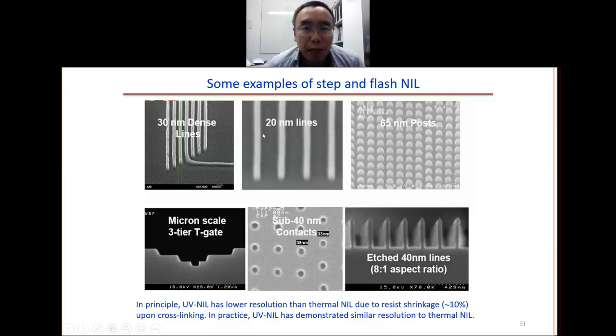Here 30 nanometer lines, 20 nanometer lines, 65 nanometer pillars, 40 nanometer holes, the 3D structures. This is etched into the silicon. So in principle, the UV imprint lithography should have lower resolution than thermal imprint lithography because of the resist shrinkage. But in reality, we got similar resolution for the UV imprint lithography and the thermal imprint lithography because we use a thin layer. So when the film is very thin, the shrinkage will not be a big problem.